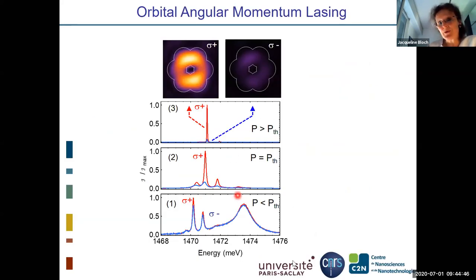So here I show you some spectra recorded looking at the total emission from such a molecule. We pump it sigma plus, and you see that below threshold, we have a very small circular polarization, typically 10-15%, but still there is a bit more luminescence in sigma plus than in sigma minus polarization. And then when you reach threshold, so you increase the power, you see that sigma plus is overcoming sigma minus, and eventually above threshold, we have really a lasing mode, which is essentially sigma plus. And you see, if we look where the light comes from, it comes really from the whole molecule, so it looks like a collective mode, and there is almost nothing in sigma minus. So indeed, we are able to lase under non-resonant sigma plus pumping.